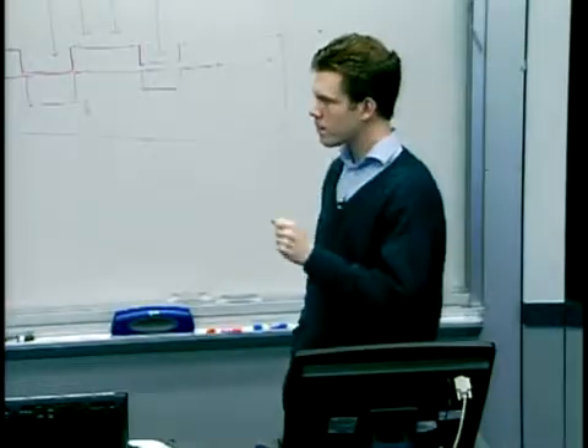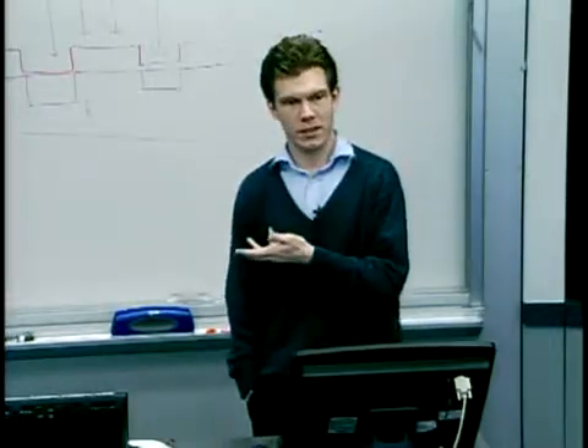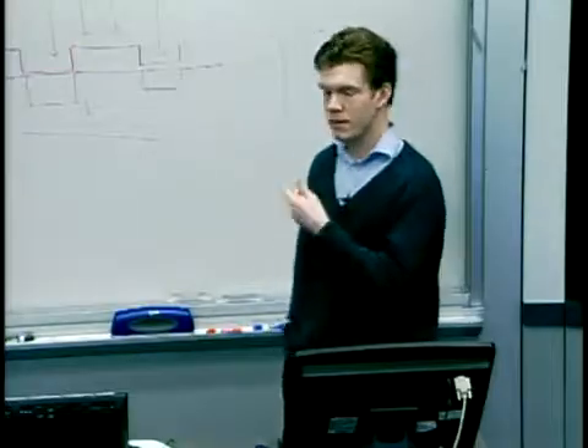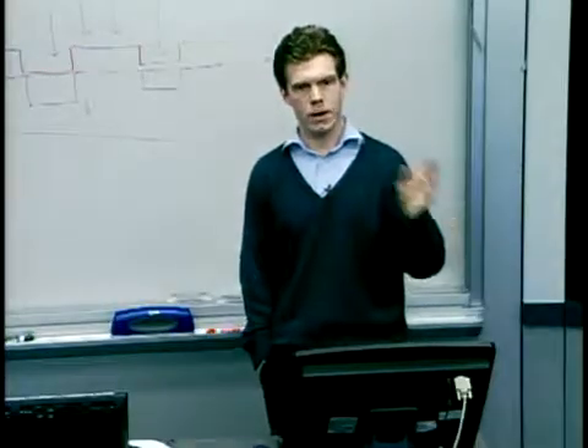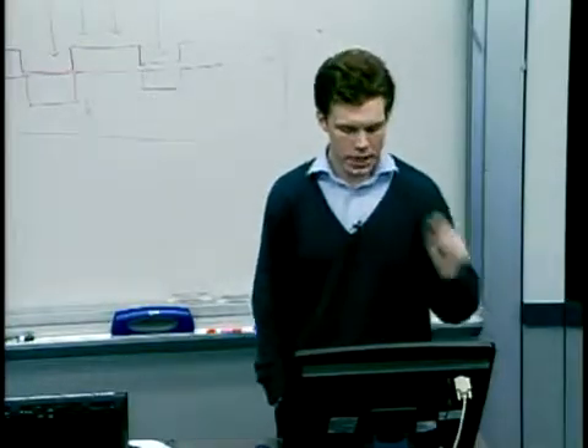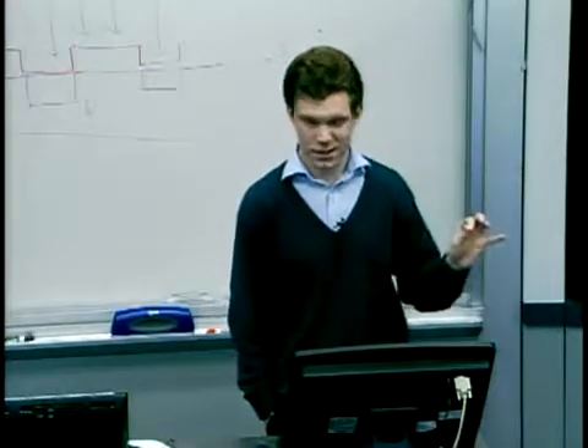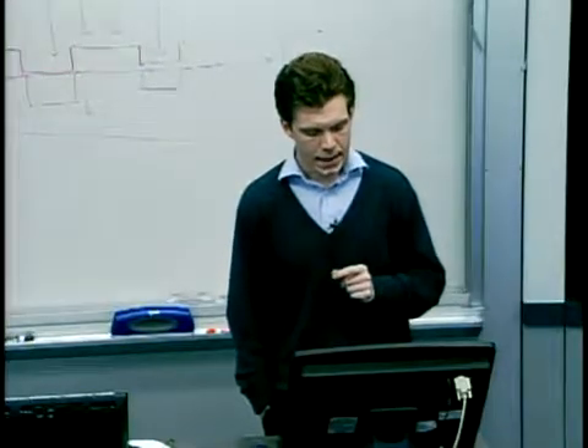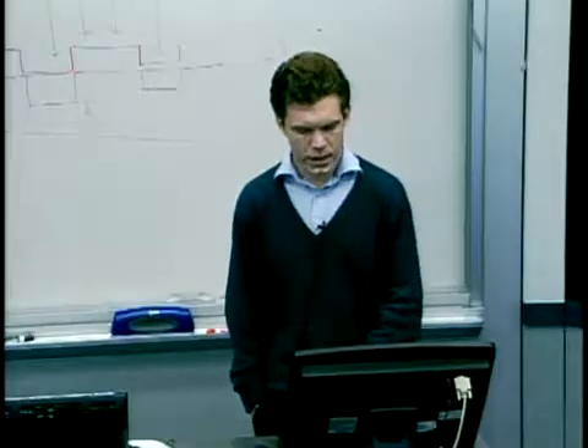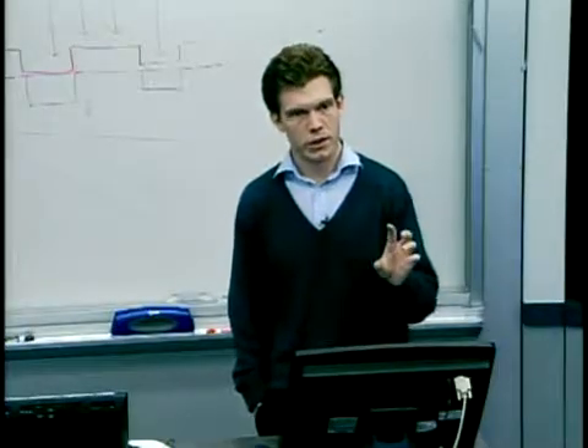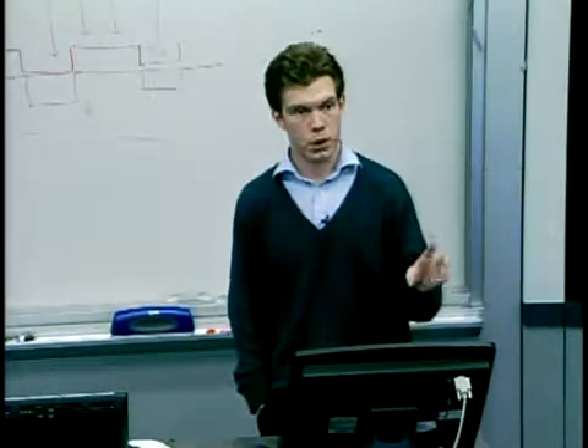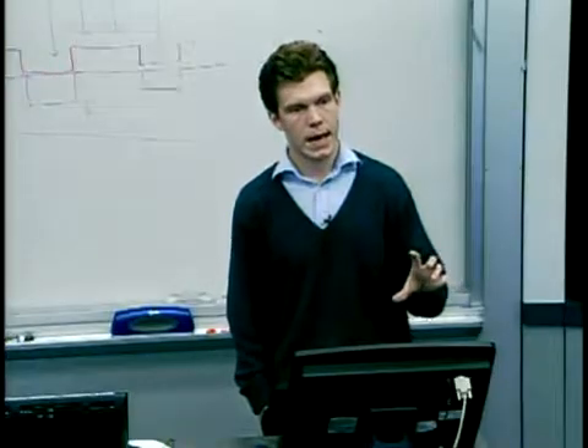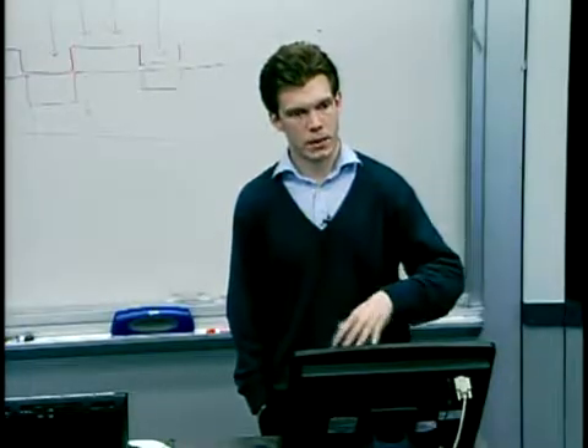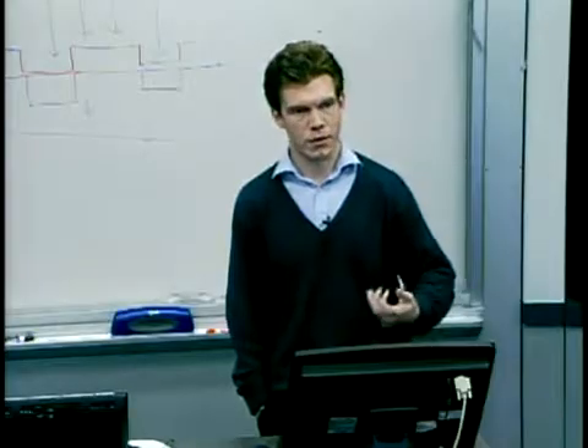But we might as well start simple and see if it works. Gives us information about what types of features replicate and what do not. So that's what we initially started with. And the idea is that increasing the temperature reduces that modulus by 3 or 4 orders of magnitude. We form the shape, then we cool down to freeze that topography in place.